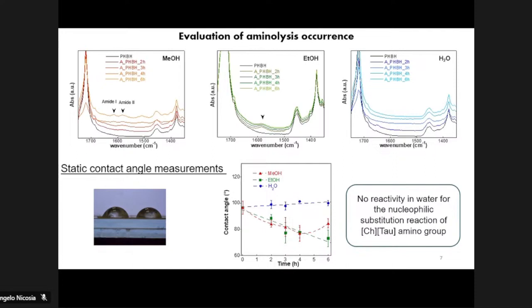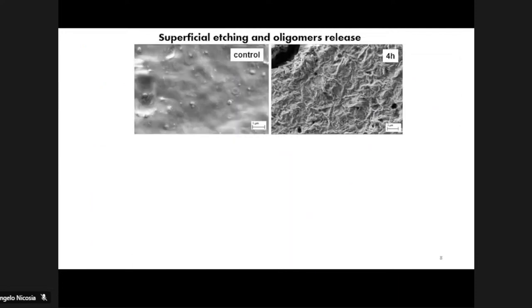Analyzing more in detail the trend of contact angles as a function of reaction time, it's possible to note that for higher times, wettability remained constant instead of increasing as we expected, and films became too fragile to be handled. So to understand what happens to the surface and to find an explanation to this behavior, morphological analysis has been conducted. Scanning electron microscopy highlighted the appearance of lamellar structures, probably due to the erosion of the amorphous surface layer.